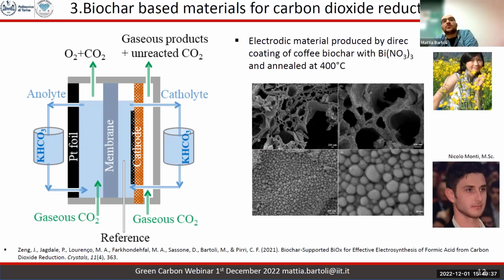One of the things that we tried in the very first place is to make a porous biochar, the one that you saw in the SEM captures here, produced from coffee waste streams, tailored with another waste stream, let's say not a proper waste stream, but a secondary product. If you think of mines, for example lead, one of the secondary products is bismuth, and bismuth is a magnificent material for catalytic activity. As you saw before, we just impregnate coffee-derived biochar with bismuth salt, and we re-anneal it to produce a bismuth oxide.